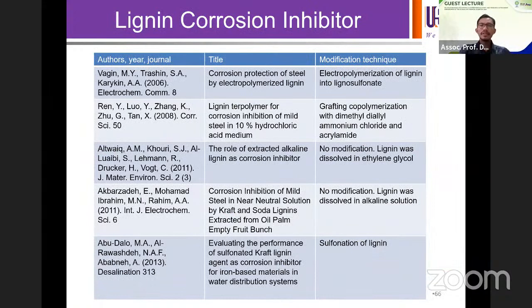And to proceed further, the modified lignin that we have obtained, we actually try to look at the application as a corrosion inhibitor. Okay. So lignin as a corrosion inhibitor has been studied by a few authors before, but I think most of them actually do some other modification in terms of electropolymerization, grafting, and whatsoever. But so far, there are no studies that have been done using organic scavengers inclusion or ultrafiltration modification.